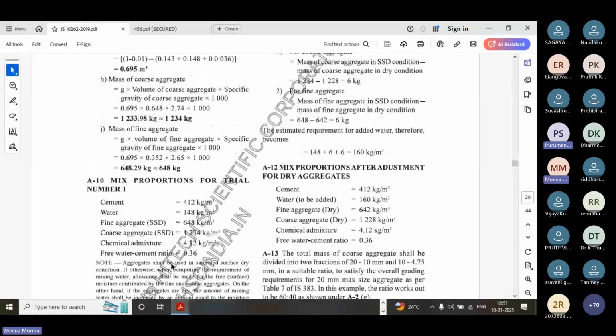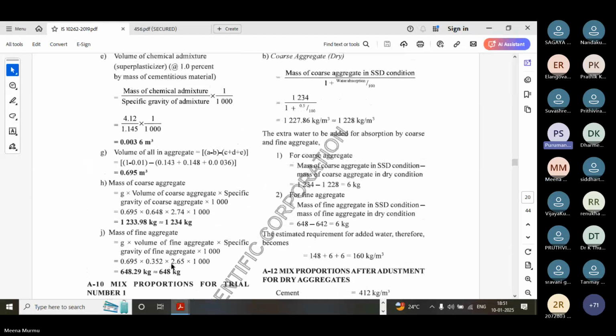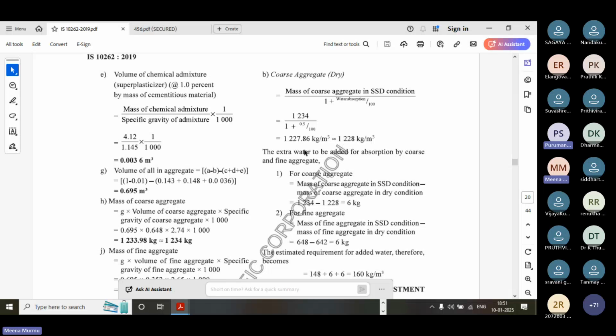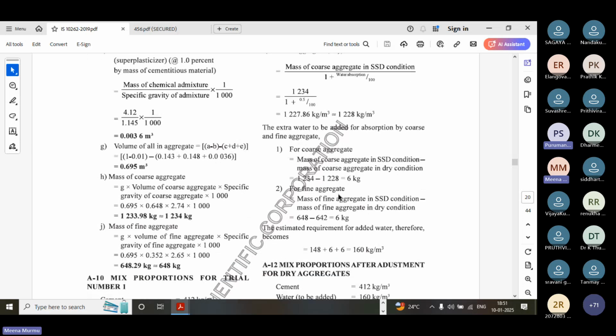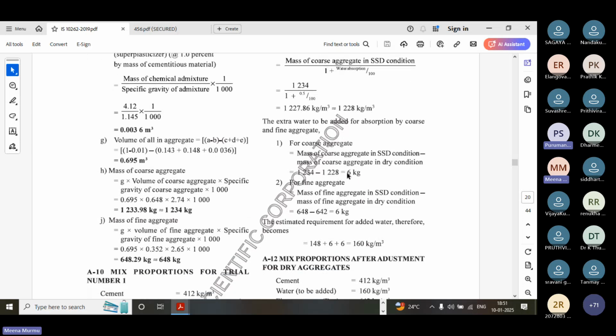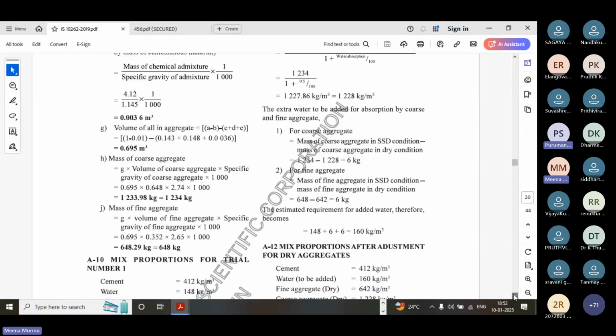We have to calculate for coarse aggregate also. This is the example for both; coarse aggregate is also reducing. Then we have to calculate how much mass is reducing. For coarse aggregate it is 6 kg and for fine aggregate also 6 kg. This is the quantity of water it is absorbing, so we have to add 12 kg of water extra. Whenever there is water absorption in the coarse aggregate, we will readjust the water quantity. And suppose moisture is there.